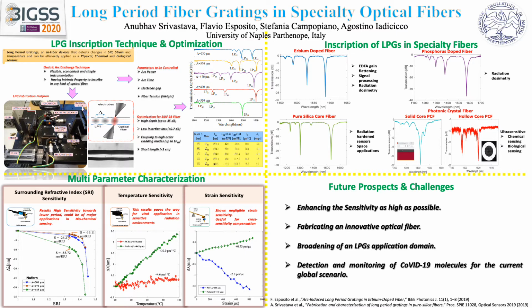Some fibers use non-standard materials. For example, there are fluoride fibers which can transmit in longer infrared wavelength regions. Also, there are phosphate glass fibers which can be more highly doped with laser active rare earth ions. Radiation resistant fibers are made from materials which are less affected by radiation and used, for example, in space applications. Also, we have active fibers as specialty fibers, which are doped with laser active ions, generally rare earth ions. We also have double clad fibers having an additional larger waveguide structure for pump light, which are even more special.